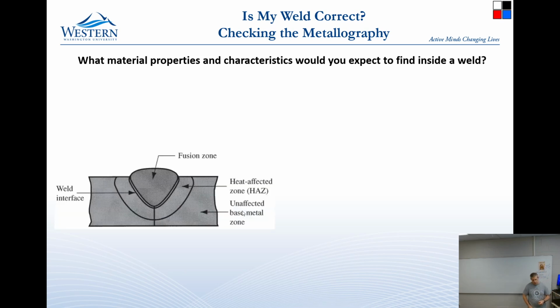So when we look at a weld, we have this area called the HAZ, the heat affected zone. And the heat affected zone is really critical to a weld because it's all uncontrolled. Actually, everything in the weld is not very well controlled. So we don't know the properties of the material that are in the weld, and we especially don't know the property of the materials that are surrounding the weld. But the thing that we do know is that this area around the weld is going to be weaker than the base material. And so that means if you are welding something together, very often the material ends up having to be thicker than you would like it to be in the end because of this heat affected zone.